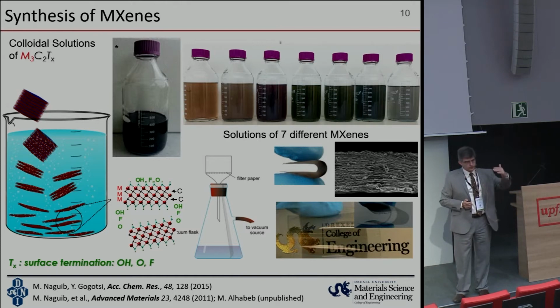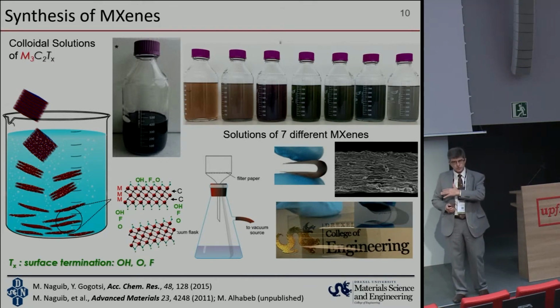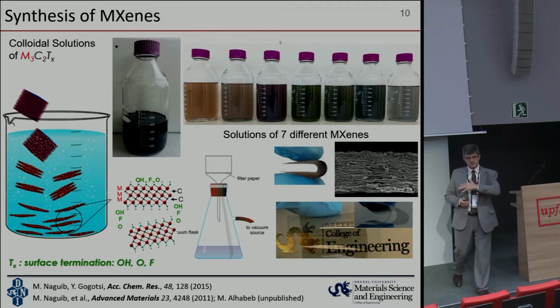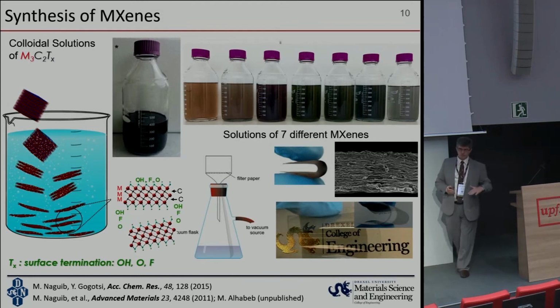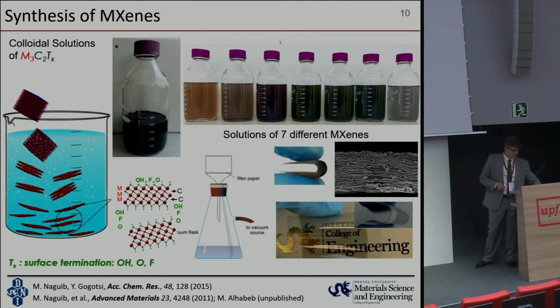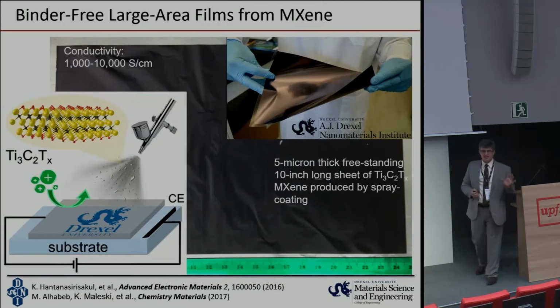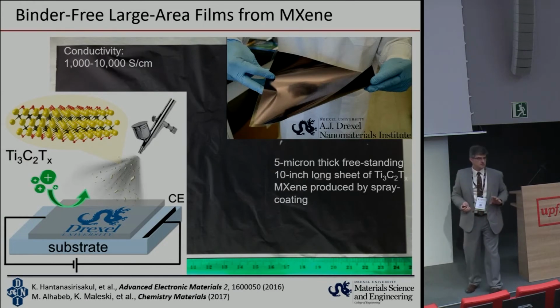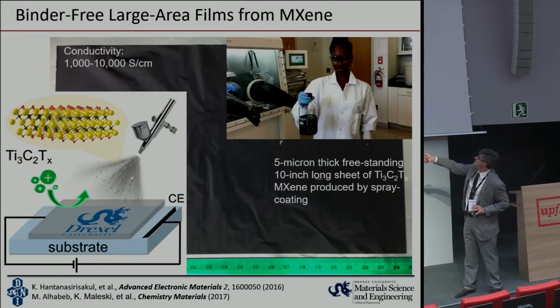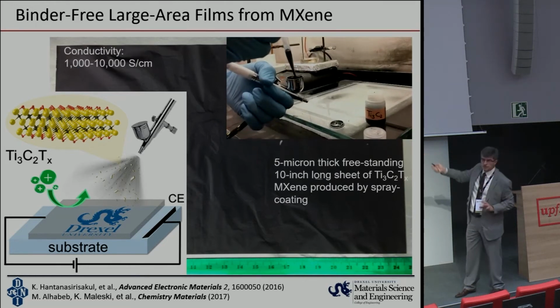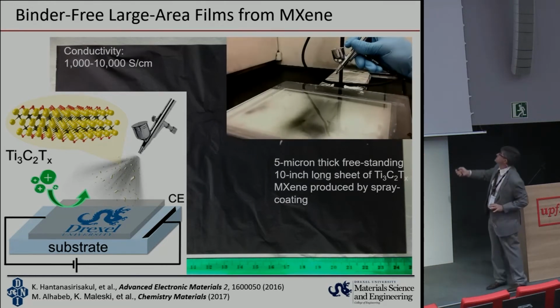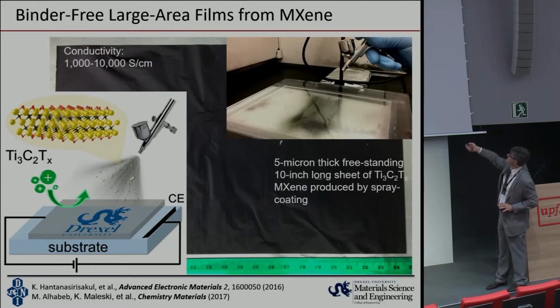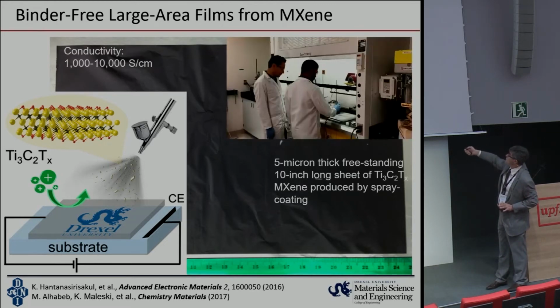So if in 1 nanometer there will be 3 graphene layers, so roughly it's a half of the absorbance of graphene. And V2C, several others are much more transparent than that. But moreover, it actually has, after solution processing, significantly higher conductivity. We get between 1,000 and 10,000 Siemens per centimeter, pushing to 20,000 Siemens per centimeter now. And this is done by simple, again, spray coating the film on the surface.